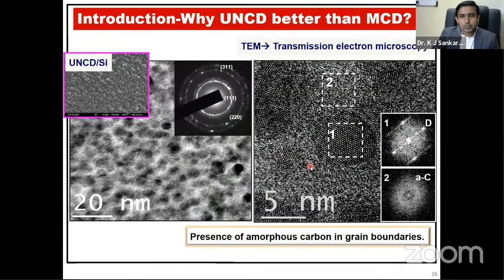So here I show the TEM image of UNCD that is grown on silicon. This is the bright field TEM image at a scale of around 20 nanometer, and this is the selected area diffraction pattern that we obtained from this bright field TEM image. There you can see diffraction rings 111, 220, and 311, which confirm the polycrystalline diamond nature. This is like the diffraction pattern we get from X-ray diffraction.